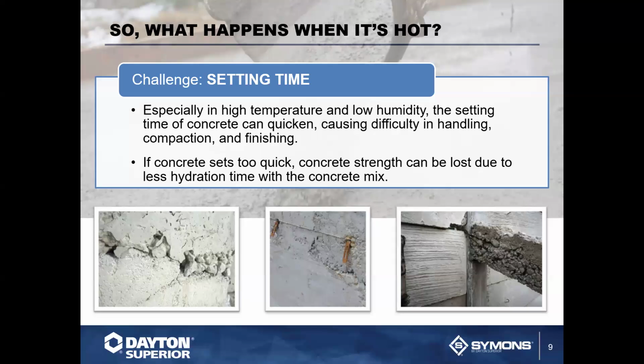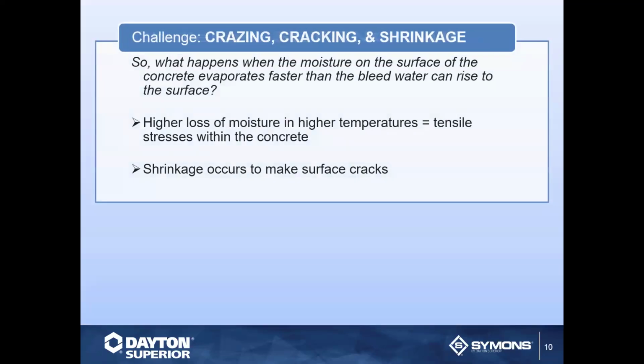As a matter of fact, I was on a job late last week, and the contractor's trucks showed up for the job. The first truck came in fine. The second truck came in with a hot load on it, and the material, when it came out of the truck, looked like a mess. Realistically, they threw that load of concrete away just because it was so thick. We're talking it was probably a 1-inch to half-inch slump. That material was that thick and that hard when it came out of the truck. So those are things that the contractors are facing today, especially with the current temperatures.